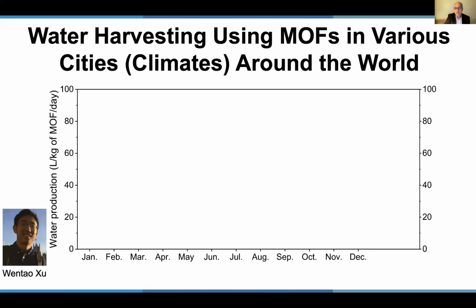The vision, based on these results with MOF 303, you can then look at the weather conditions in any part of the world and calculate how much water is going to be harvested using our experimental results as basis. So the Atacama Desert is the driest desert in the world, and you see that at the driest time of the year in August, you can still harvest about 5 or so liters of water per kilogram of MOF. And I want you to also note that the MOF stays in the device for the lifetime of the device, which is 5 years or so.